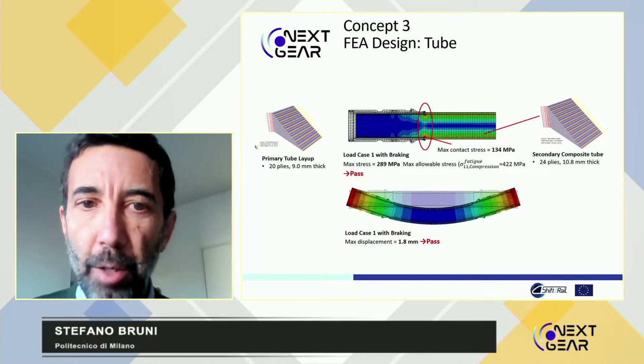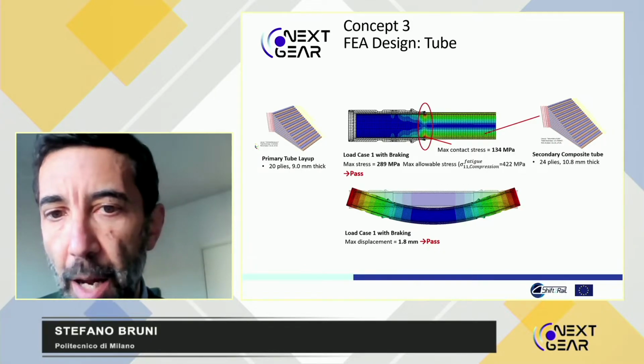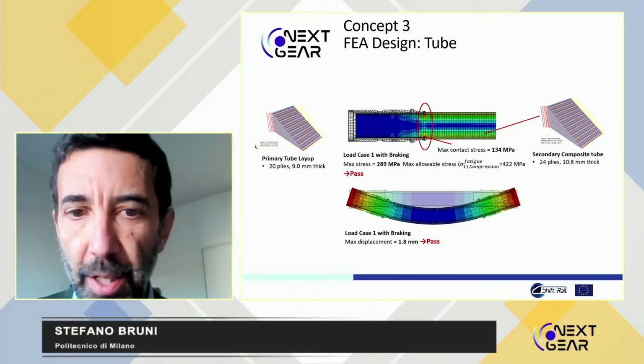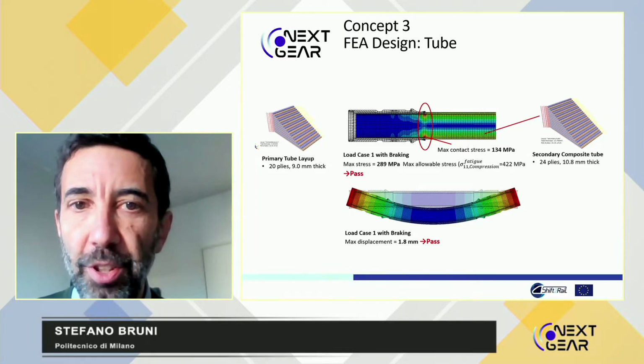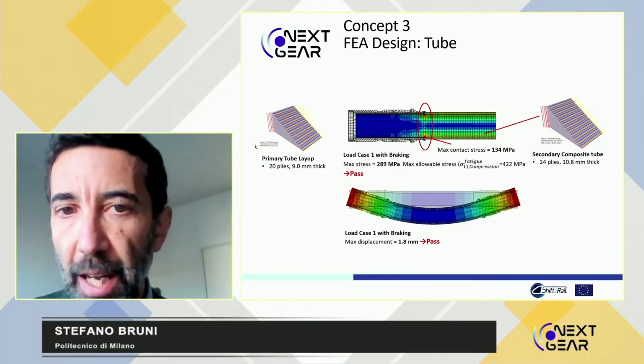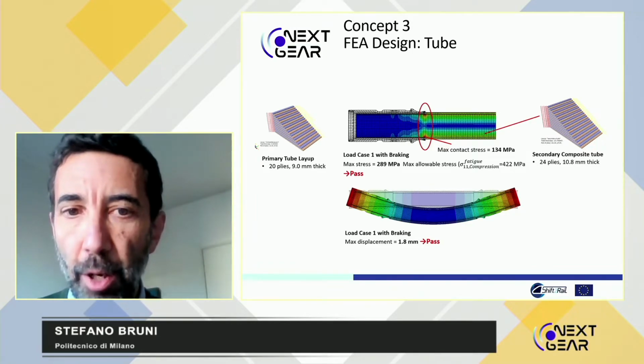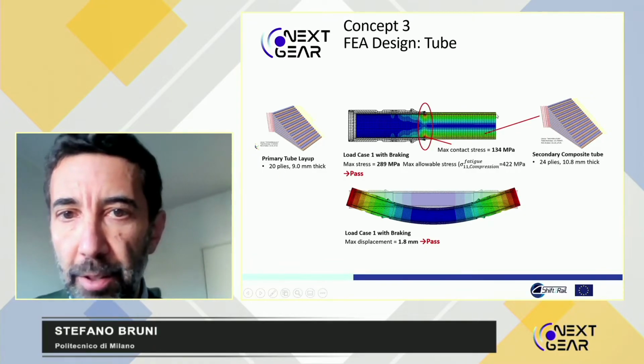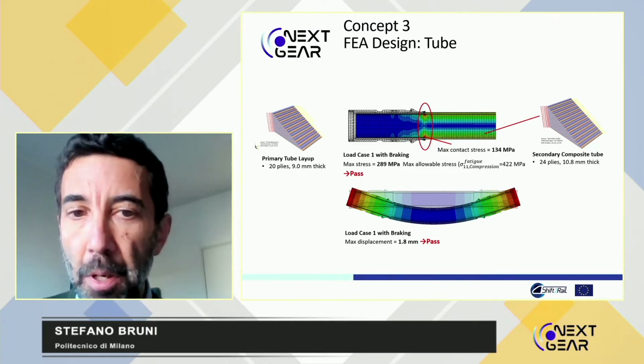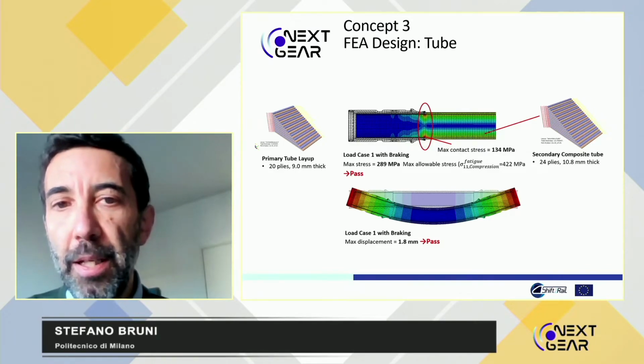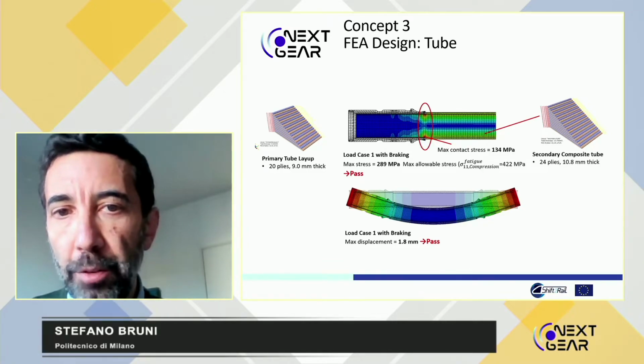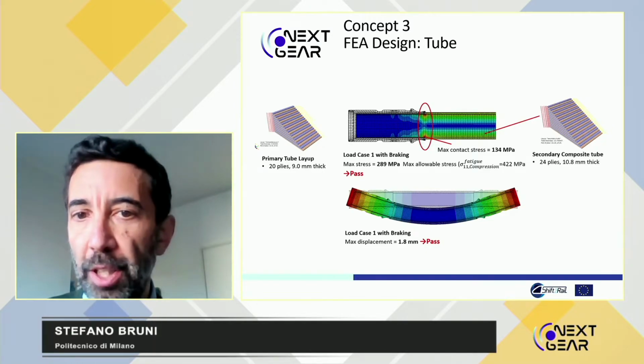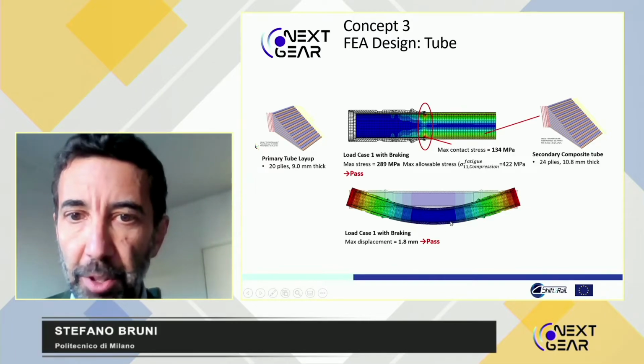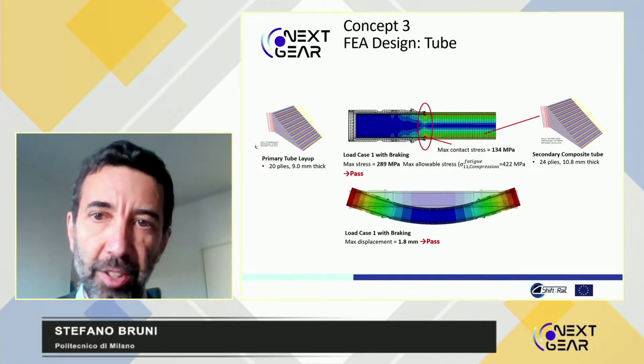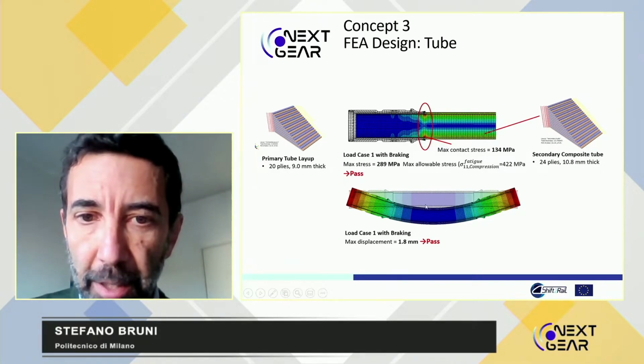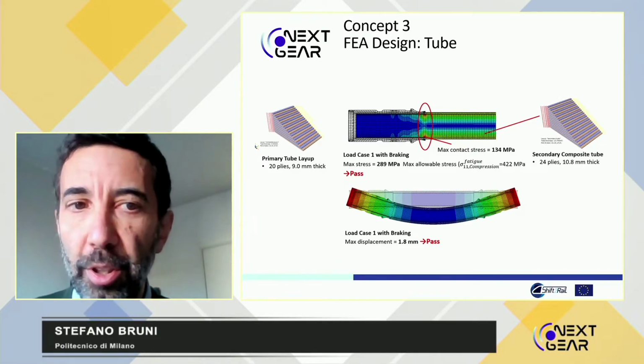One important point was about making sure that the hybrid metal composite axle could meet the flexibility, or bending stiffness, targets, for which we used the steel axle as a reference. And that was the part of our work where we realized that by just using the inner full-length composite tube, we would end up with possibly too flexible an axle. It may be a subject for further investigation whether one could accept this higher flexibility as long as it is not impacting, of course, on the structural resistance of the material. Here, the problem was not really with the maximum stresses exceeding the limits, but rather with the maximum bend deformation exceeding some limits that we decided internally in our work.